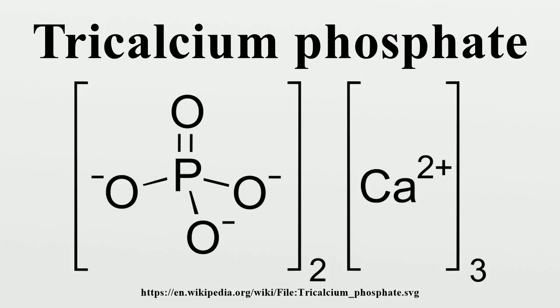It is also found in the skeletons and teeth of vertebrate animals, and in milk. Biphasic tri-calcium phosphate (BCP) was originally reported as tri-calcium phosphate, but X-ray diffraction techniques showed that the material was an intimate mixture of two phases: hydroxyapatite (HA) and beta-tricalcium phosphate. It is a ceramic preparation involving sintering, causing the irreversible decomposition of calcium-deficient apatites, alternatively termed non-stoichiometric apatites or basic calcium phosphate. Beta-TCP can contain impurities such as calcium pyrophosphate (Ca2P2O7) and apatite.